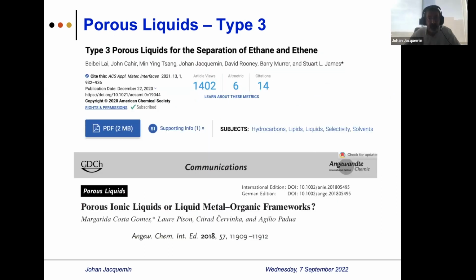And as I mentioned, I was in Belfast and I had the chance to work with this group, and we measured porous liquid for separation of ethane and ethylene. And then the group of Margarida Costa Gomes also published a type 3 porous liquid by mixing ionic liquid and ZIF-8, basically. And it was a zeolite imidazolate framework as well.